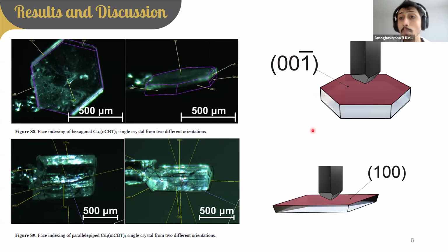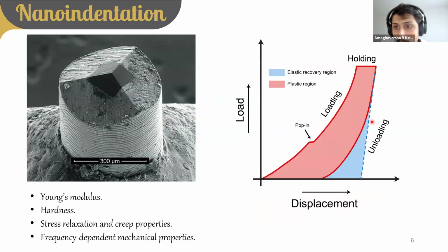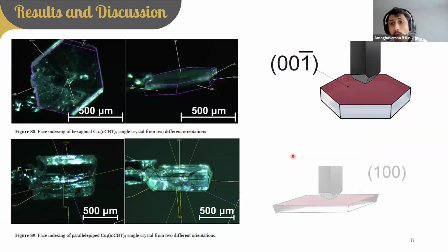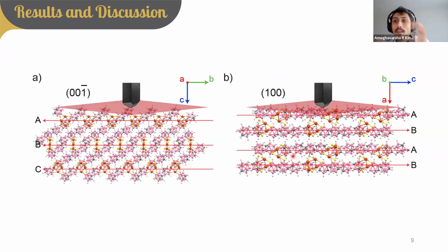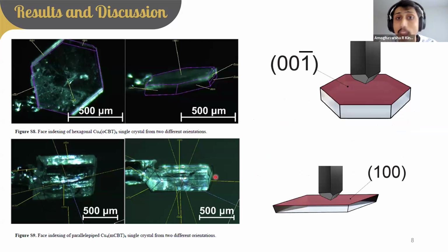So Young's modulus and hardness values won't change much, because as I showed in this, the slope of the unloading curve, where the material is relaxing, is what gives us the property of the material, and not the loading curve. Whenever you are putting pressure along different faces, the tip may go into the material in different ways, but when they relax, the material relaxes in complex ways: acoustic vibrations, thermal vibrations, then rotation of ligands. In this paper itself, I have shown that in Cu4(oCBT)4 the ligands rotate like this, and when they relax, they come back like this. But in the case of Cu4(mCBT)4, the whole cluster compresses and then expands. That is what we have shown through computation. So the relaxation method can be slightly different depending on direction, but not much different when we get the Young's modulus and hardness values.